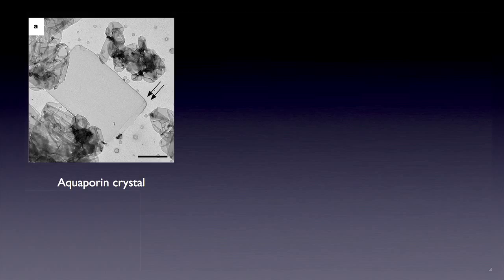So the best way to proceed is to record a lot of images of crystals, but also a lot of diffraction patterns directly. For instance, in the aquaporin crystallography project, many images were recorded of these crystals. This is obviously an image. You can see the double layered nature of that crystal. From an image like this, a Fourier transform would reveal both amplitudes and phases along all the lattice lines.